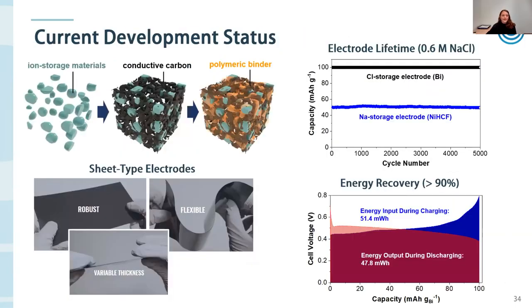And so when we make both our nickel hexacyanoferrate and bismuth electrodes through that electrode fabrication method that I showed on my previous slide, we can achieve stable performance with both electrodes for over 5,000 cycles. Again, over a year of continuous operation in these sodium chloride solutions that have a salinity approximating that of seawater.